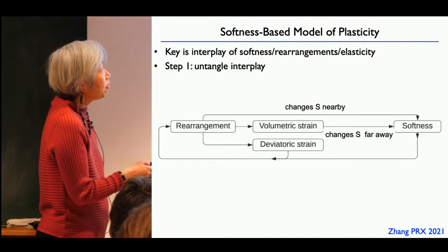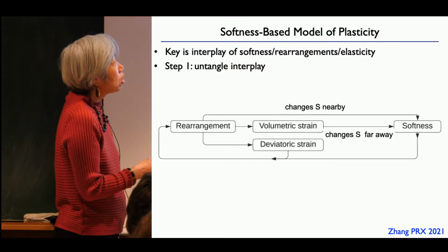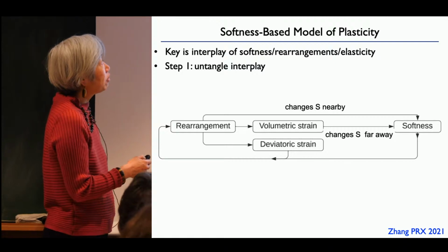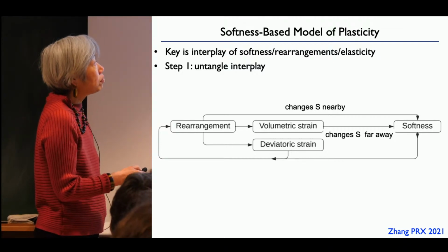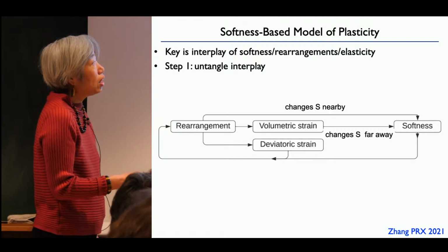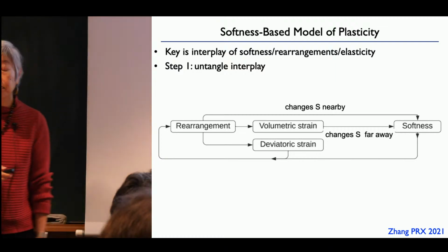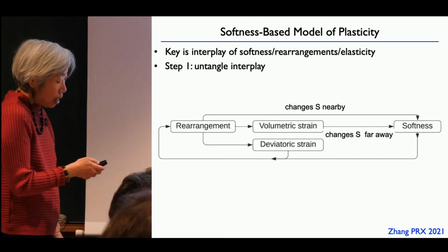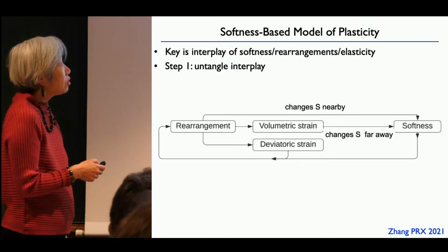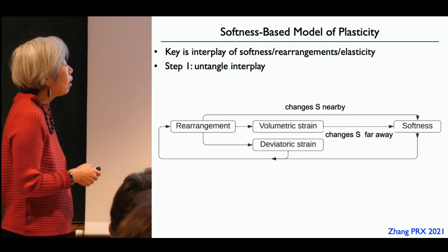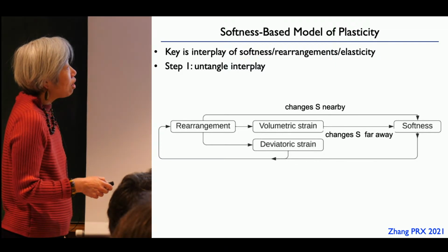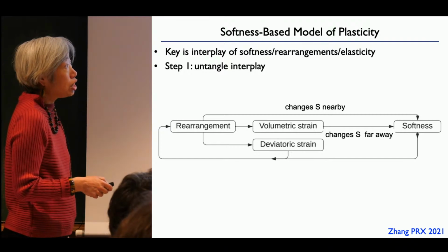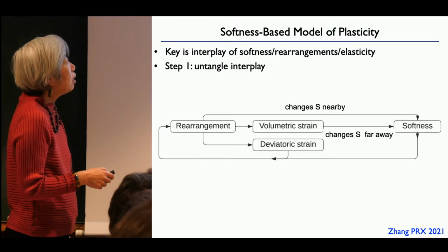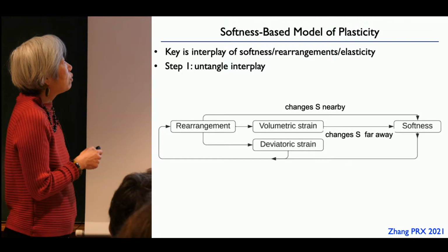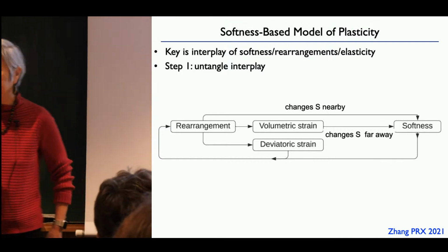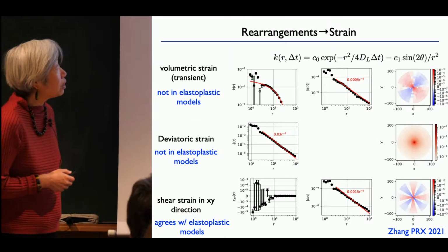So there's this direct effect on the softness nearby. There's also a far field effect, so that's a near field effect. There's a far field effect coming from, it turns out, the volumetric strain, which changes the softness far away, okay? And then the rearrangement also gives rise to a deviatoric strain, and that combined with the softness, which determines the yield stress, can push you over the edge to have another rearrangement. So that's the model.